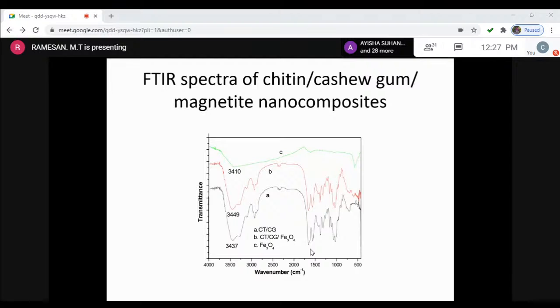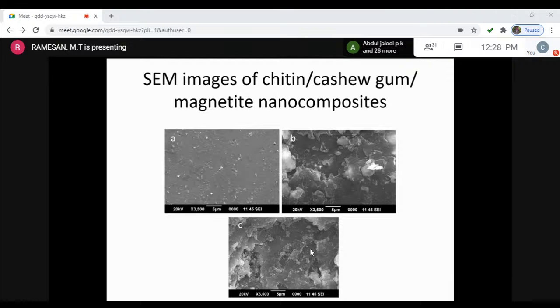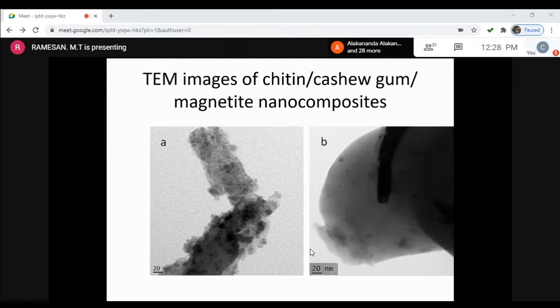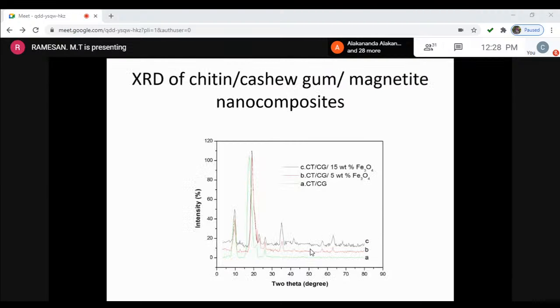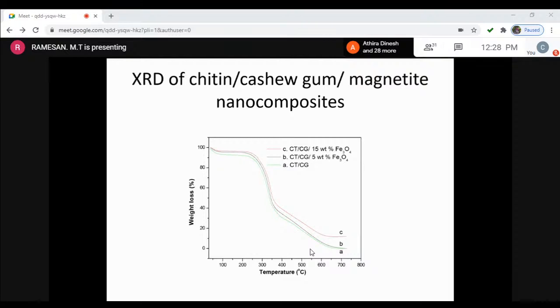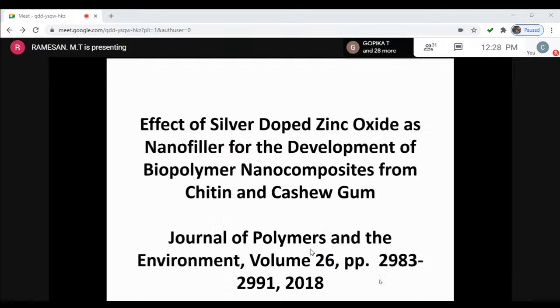This is the FTIR spectra. The FTIR spectra show the presence of magnetite nanoparticles in this system. SEM images of this chitin cashew gum show the presence of magnetite nanoparticles in that system. The XRD of chitin cashew gum also shows this nanoparticle system. Here also, the thermal stability of chitin cashew gum is greatly improved by the addition of iron oxide nanoparticles into this biopolymer system. Next is silver doped zinc oxide as a nanofiller for the development of biopolymer nanocomposite from chitin and cashew gum.